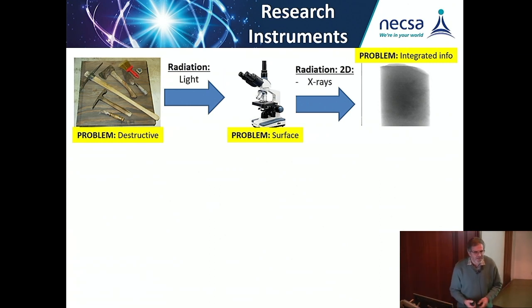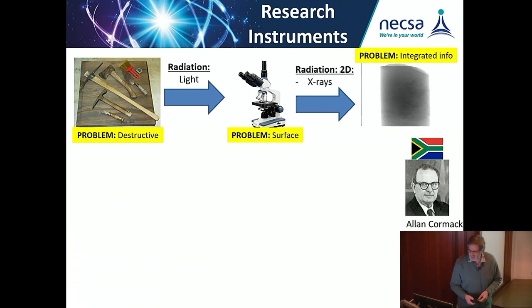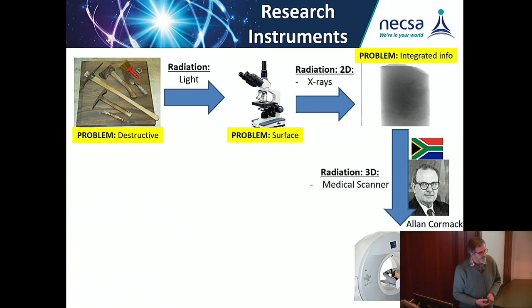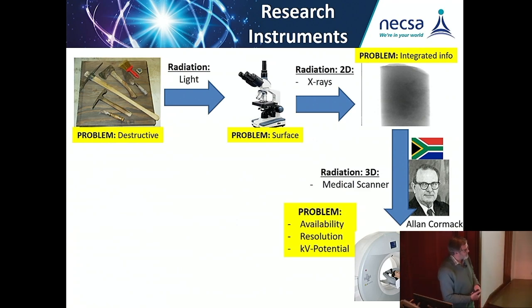So the problem persists. What happens is there's a rescuer, namely Alan Cormack, a South African physicist, that invented the CAT scanner that we have at all universities, or most of the hospitals have the CAT scanner. But did the CAT scanner, which is located at hospitals, eventually give us the needed information? Actually not, because those CAT scanners are merely available for human patients. As well, the resolution in the order of half a millimeter is not enough if your object of investigation is 50 micron. So effectively, even though it's also fixed with a certain potential kilovolt energy, effectively you are stuck again.